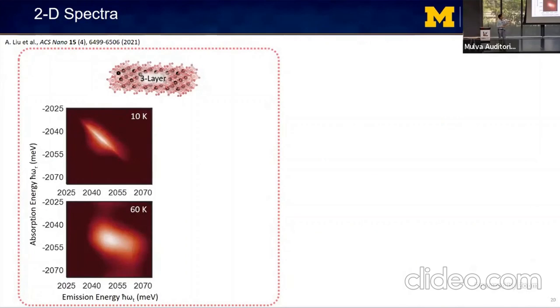So this is what the 2D spectra look like for our 3-layer nanoplatelets at temperatures of 10 and 60 Kelvin, where we observe textbook inhomogeneously broadened resonances. And as a reminder, the line shape in the elongated direction reflects the inhomogeneous line width, while the line shape in the cross-diagonal direction reflects the homogeneous line width at a given resonance energy.